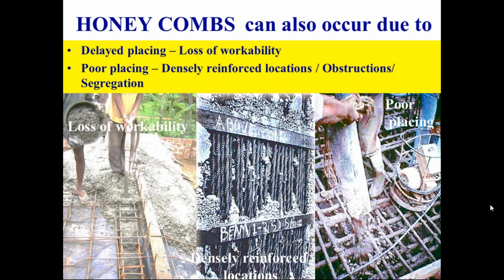Poor placing due to densely reinforced beam column junction. You can see here, this is a very interesting view. You can see the concrete cannot even go through the bars. It's a barrier of reinforcement bars. It was not planned properly. And the third photograph shows pumping of concrete against obstruction of reinforcement, clearly showing segregation. The result is that the mortar sticks to the bars and the aggregates fall below, causing honeycombing.